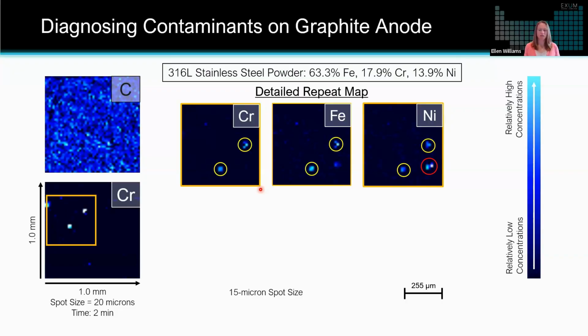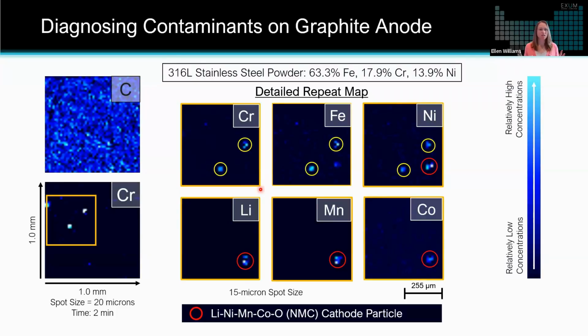But what was unexpected in this study was this third particle that you can identify on the nickel map that does not have high chromium, doesn't have as high of iron. And so because of the advantage of the time of flight, where we're seeing all of the elements, whether we want to see them or knew to look for them or not, we can then take a look at those other elemental maps and see that we've got high lithium, manganese, and cobalt in that third particle that we've highlighted in red. And based on that chemistry, we determined this was actually an NMC cathode particle. So an unexpected contaminant particle was identified by this technique.